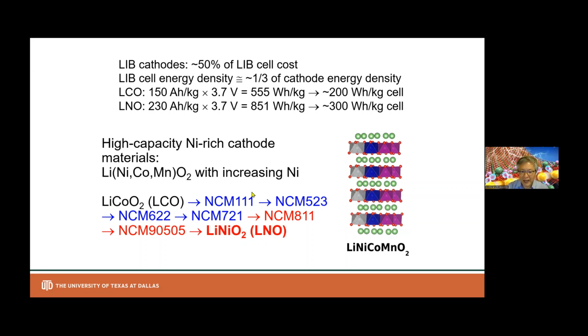Nickel was added to increase the capacity. Nickel has a double redox reaction. In this formulation, as you can see, nominally lithium is 1 plus, the nickel, cobalt, manganese overall average is 3 plus, oxygen is 2 minus, so those 3 plus charges stay, but manganese is 4 plus, nickel is 2 plus, so the nickel can go to 2 plus, 3 plus, 4 plus during the lithium deintercalation, so that it has higher redox capacity leading to higher energy density.